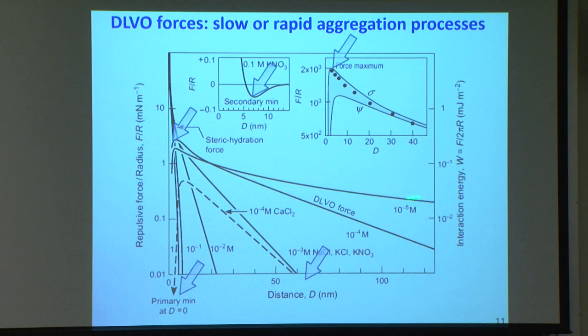So if you have a dilute solution, you have a repulsion, and then eventually the van der Waals forces, and then you get attraction and adhesion in contact. That's theoretically. As you increase the electrolyte concentration, the repulsion comes in closer in, and you can get what's known as a secondary minimum adhesion, or an attraction that wins out, and then the repulsion wins out, and then the attraction. That's the interesting consequence of this theory: because you have one force that goes exponentially and one that is a power law, you can get repulsion, attraction, or, usually, attraction, repulsion, then attraction. That's the basis of colloid science and biocolloidal systems. When systems adhere, are they adhering out here at a weak minimum, or are they coming into contact?